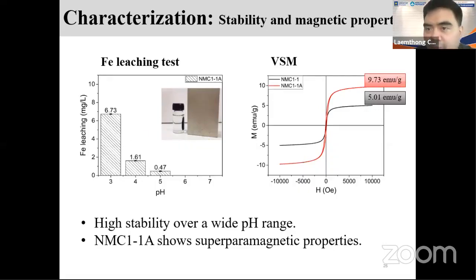This is still a limitation of magnetic adsorption at the moment, because if you have a quite acidic system, it can leach out your magnetic particles. That means you will lose your iron species, because in this case I use iron. But if you use nickel or cobalt as the magnetic particle, you can also have the same problem under acidic conditions. But of course, up to pH 5, we can still use it. We actually can have a little bit of iron leaching from the system, but not so much anymore.